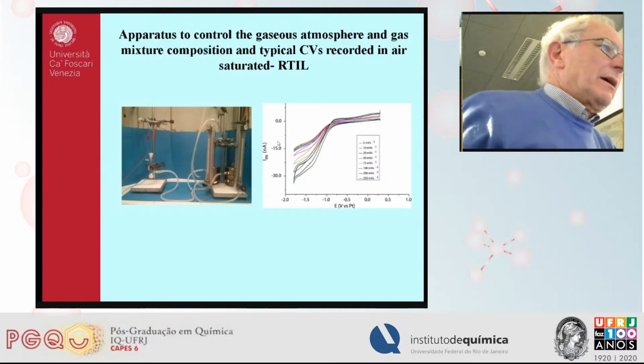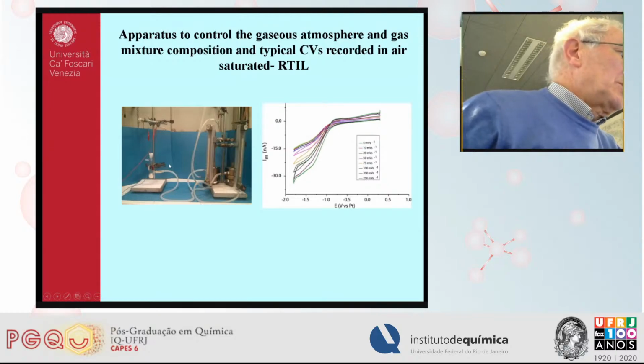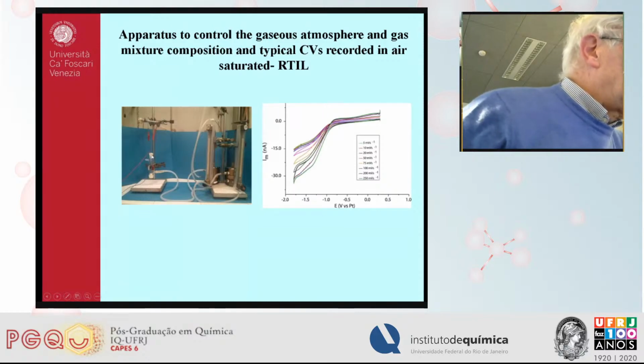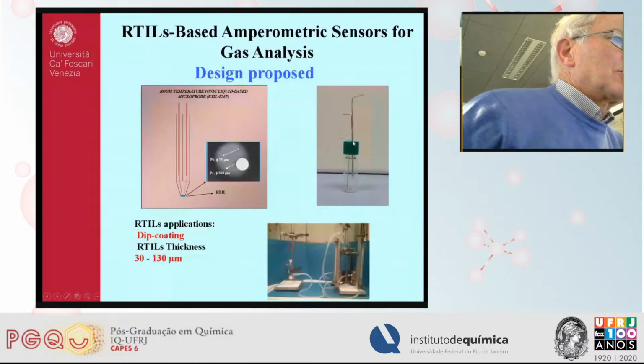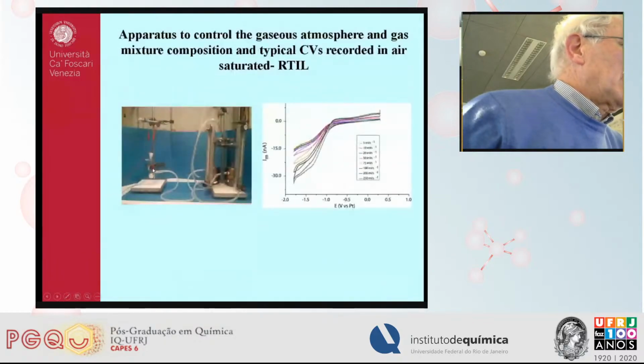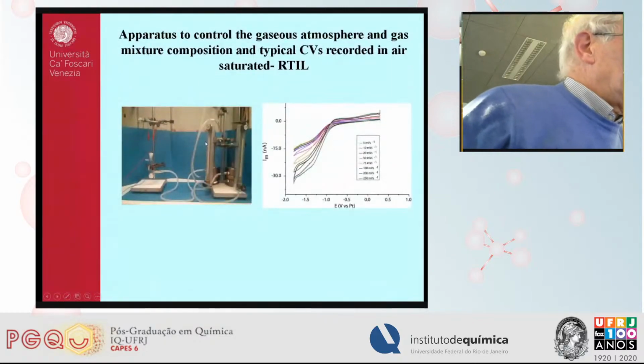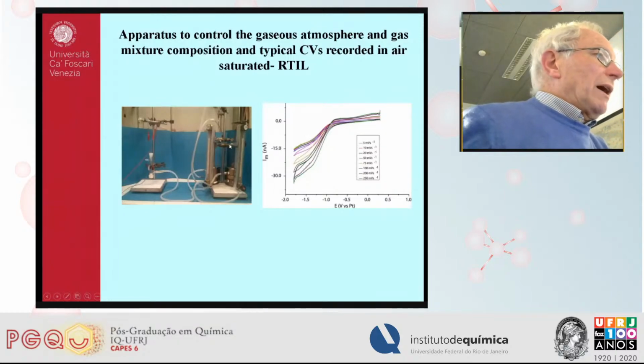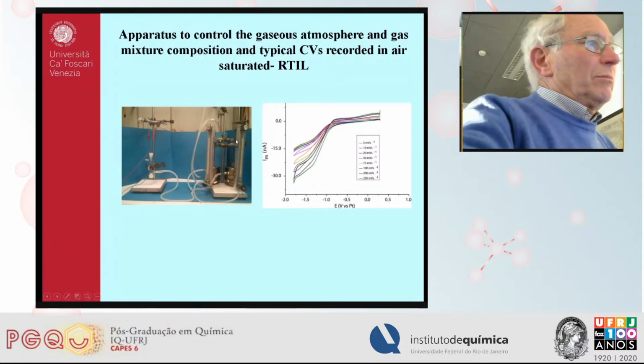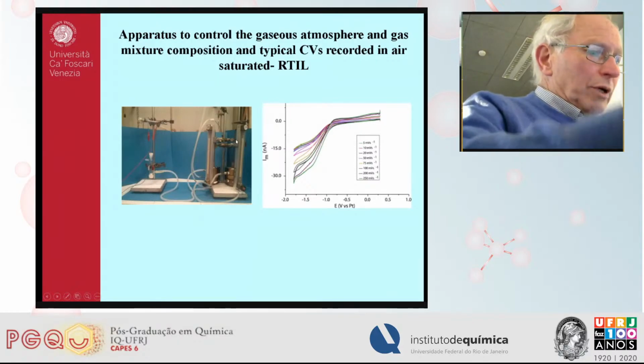and these are typical responses obtained for the oxygen reduction in gas phase with the system. Okay, here is the container in which we put our probe. I don't know if you can see the probe here. Anyway, it's inserted. This one was inserted in this container, and by this system we could provide the adequate mixture of oxygen with nitrogen.